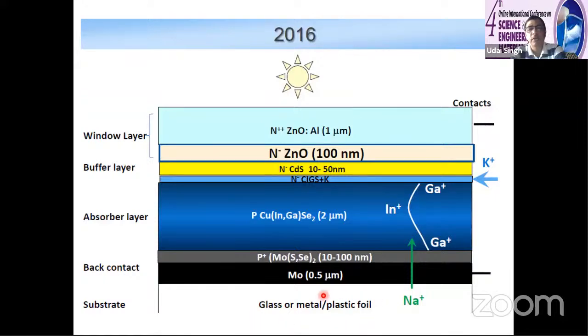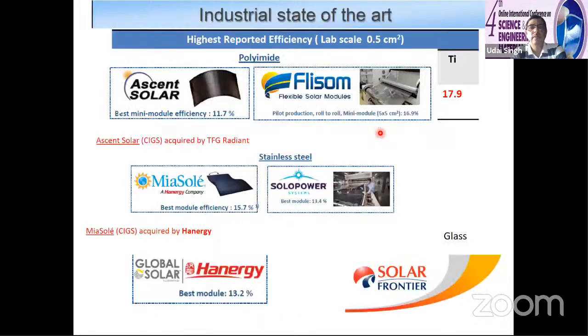You have a glass or metal or plastic foil, then you coat the moly as a back contact, then you have the copper, indium, gallium selenide. During the process, you form some moly sulfide or selenide. Then you have some post-deposition treatment of an alkali metal like potassium. Mostly people are using potassium. Then you do the cadmium sulfide, and then the zinc oxide, which is your intrinsic zinc oxide. Then on top you have the highly doped zinc oxide. So that is the structure people are using.